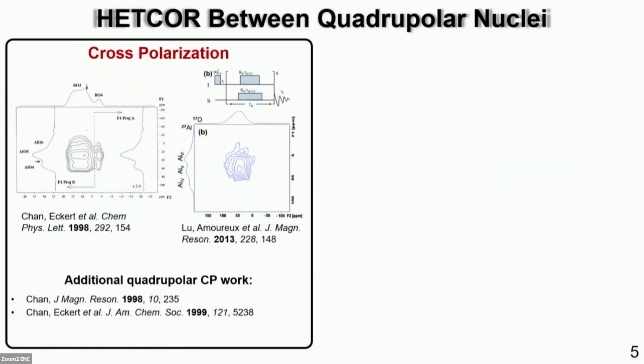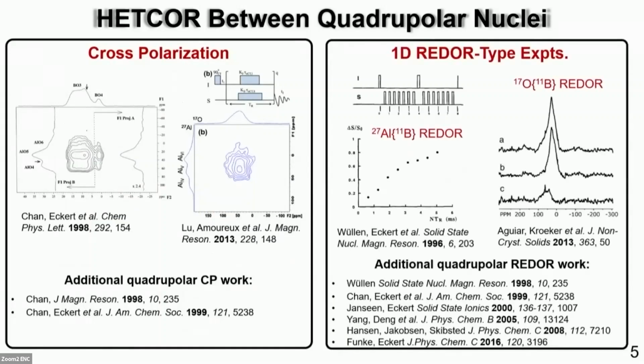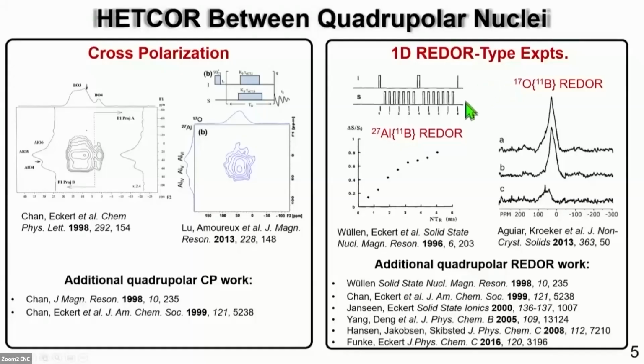People have shown that you can do cross-polarization between half integer quadrupolar nuclei. However, this is going to be highly sample and site dependent, and you might not observe some expected correlations. For a few decades, there have been groups applying dipolar recoupling to half integer quadrupolar nuclei to obtain these heteronuclear correlation experiments, but this has been primarily limited to 1D REDOR type spectra, such as these dipolar dephasing curves, or just 1D filtered NMR experiments.